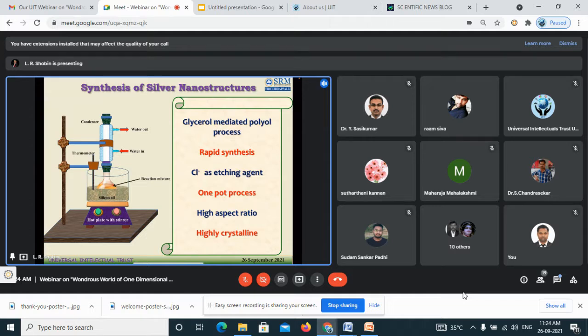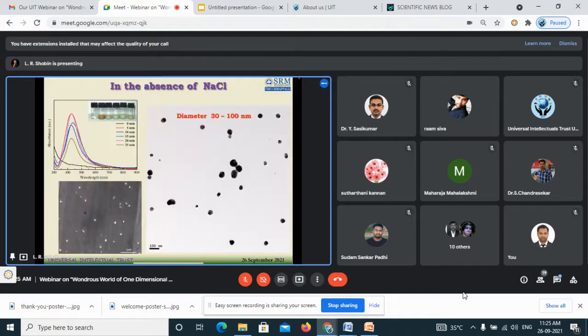I use chlorine as an etching agent. For that I use sodium chloride as an etching agent. You mix everything together and heat it up, and you will end up with silver nanowires. So it's a one-pot process. You don't need to go for a step-by-step process. You mix it together, heat it up, and you will get your nanowires. These wires are highly crystalline in nature, and they have a high aspect ratio too.